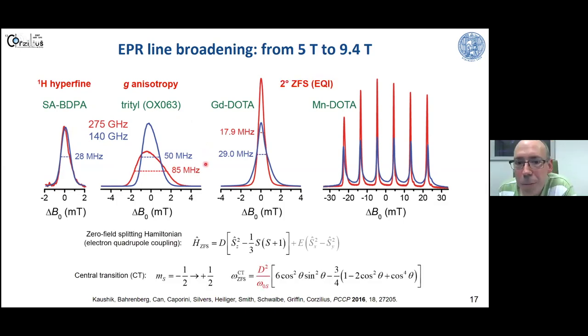And with these high spin metal ions, gadolinium and manganese, if you only look at the central transition, and this is what we can use for DNP, we see an effective narrowing of this central transition due to the reduction of the contribution of the second order effect. And at this point, sorry for being a little bit long, I would like to make a break and would be happy to answer some questions.